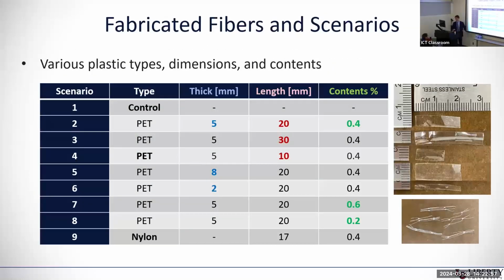So this shows the scenario: the types of plastics, the dimensions and the contents. We had a control mix without any fibers, and then PET with fiber widths of 5 millimeters, and then 2 millimeters and 8 millimeters, with different thicknesses of these fibers. And also we had 3 different lengths of fibers, from 10 millimeters to 30 millimeters. And we had various fiber contents to see the effect on asphalt performance. As you can see here, we fabricated this manually, so we didn't use a shredder because it's really hard to control the shape.